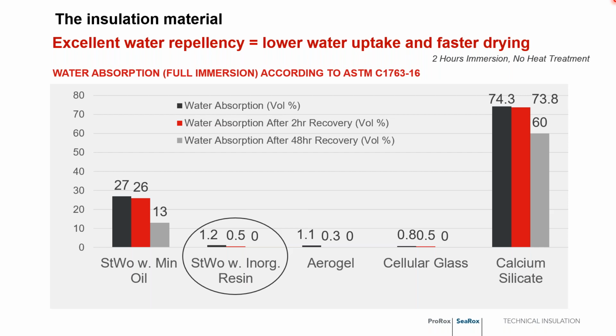You may be wondering how this test is different from the previous G189 test. Well, this test only looks at water absorption into the materials, whereas the G189 test looked at water escaping. So that's, again, back to the closed cell versus open cell. With the G189, we can see how fast water could escape through the different cellular structures of the insulation.